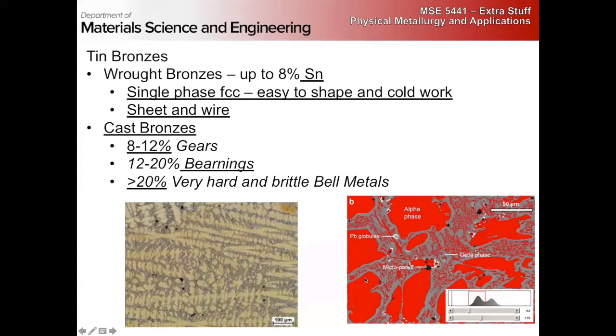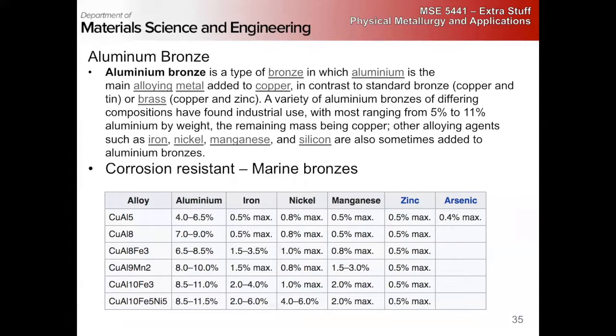Even as bells and cymbals, they sometimes crack. This mixture of alpha and gamma is somewhere in the 8 to 20% range. Bell metal has some lead globules, alpha phase, gamma phase, some porosity, and other inclusions. Those are the classical bronzes.